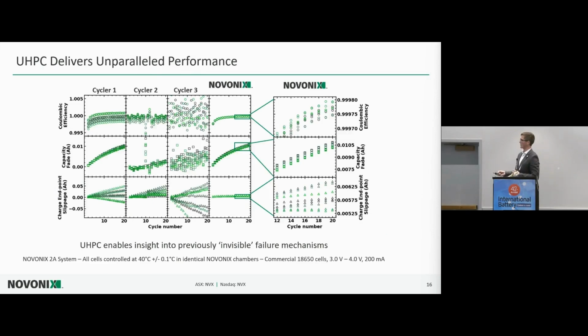And if we look at what this looks like with identical cells on these different systems, you can see that these biases, the accuracy of counting between charge and discharge, are really poor. So both the accuracy and precision are very important. We can really only get this type of measurement using UHPC.